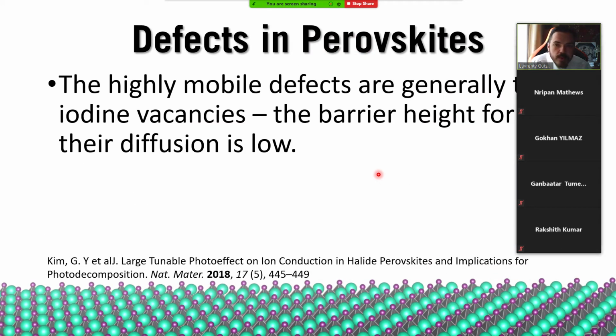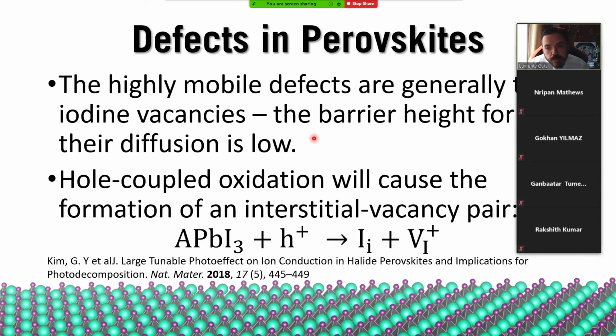The most mobile defect by far is the iodine vacancy. The barrier height is very low, maybe 0.2 eV. It's even lower if we choose a configuration where the methylammoniums are oriented ferroelectrically or anti-ferroelectrically. In that case, it can be almost nothing. So these defects are very highly mobile.